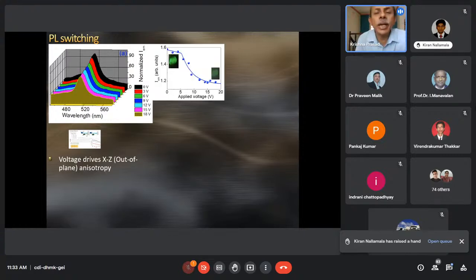And as I said, you can electrically switch these systems and change the fluorescence. Visibly, you can see the change switching between a very bright state to a very dull state going to the high field regime. So therefore, you can control the magnitude of the fluorescence change continuously in a grayscale kind of situation, going from a very bright to a very dull state. So therefore, you can in principle create display devices which are fluorescent liquid crystal devices.